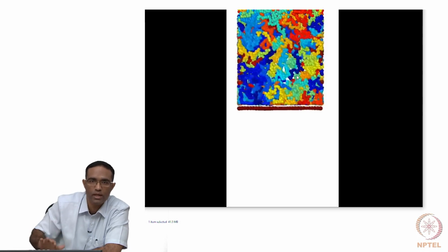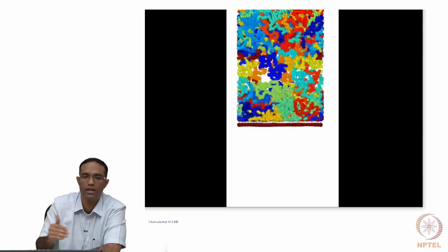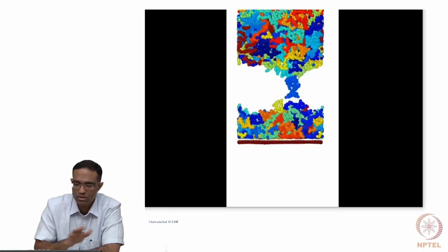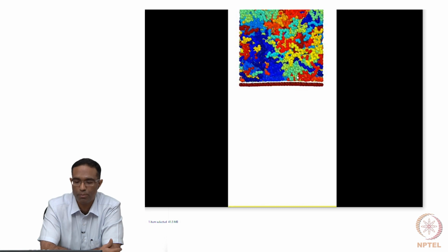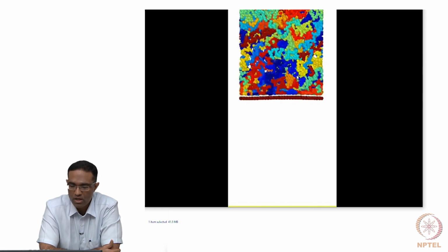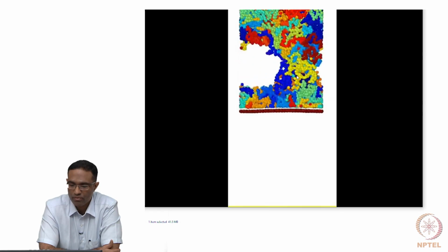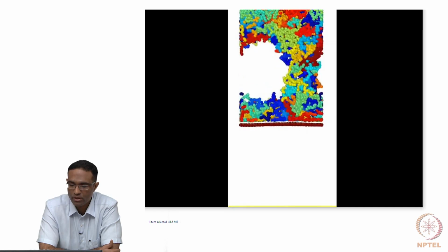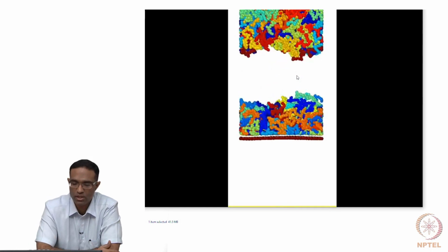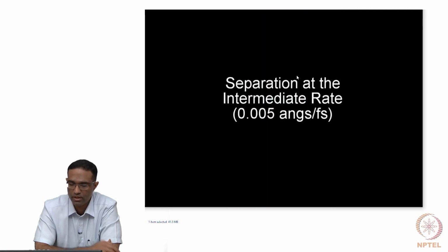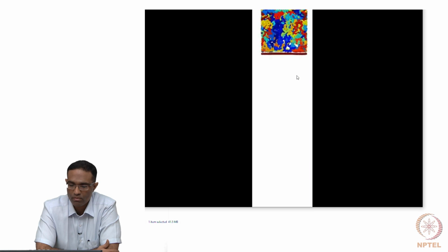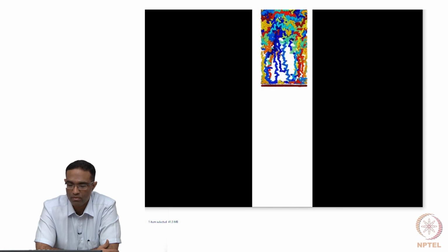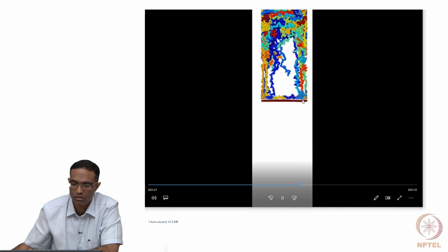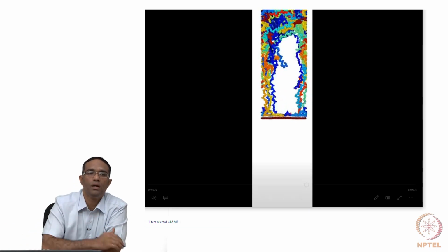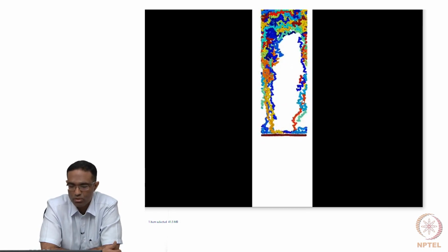The rate at which you are seeing this being pulled and the rate at which the simulations are performed need not look the same. Things have been rescaled so that the video appears within a reasonable time. So this is at some specific rate, and you see that the failure is happening somewhere in the middle of the polymer. This is at somewhat intermediate rates. That is the behavior that you see, with chains being pulled to a longer extent, slightly faster separation. At intermediate rates, you see more polymer chains being stretched, and some of them still connected to the graphene surface over here. So depending upon the rate at which you pull the polymer, you see different behavior, and that's what is being captured by these simulations.